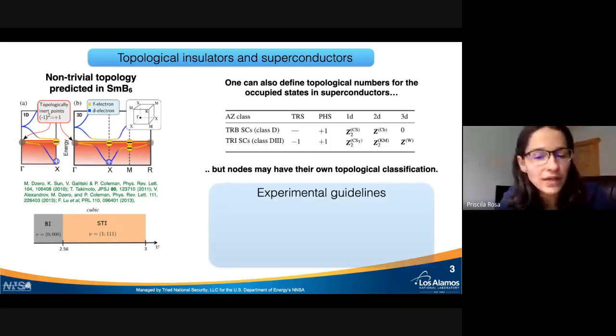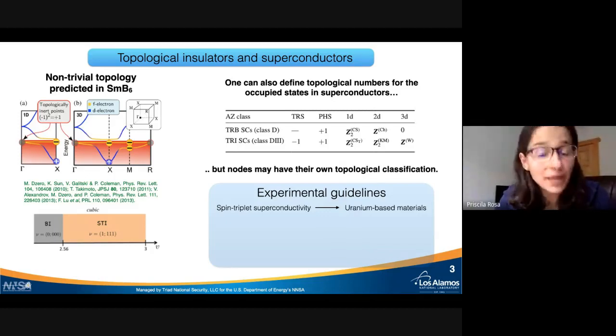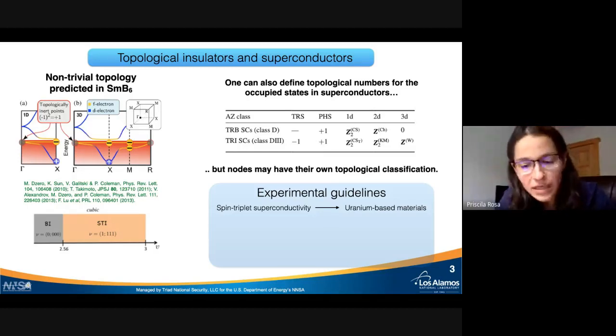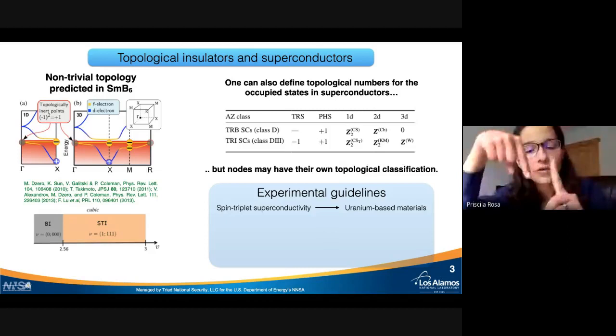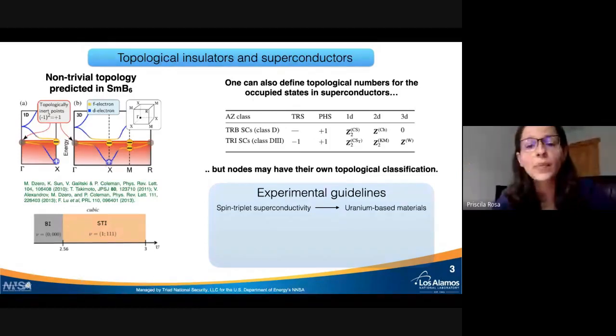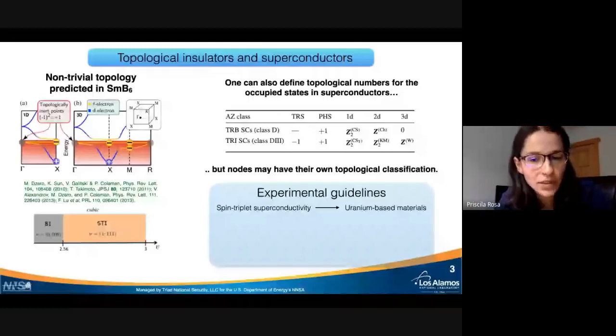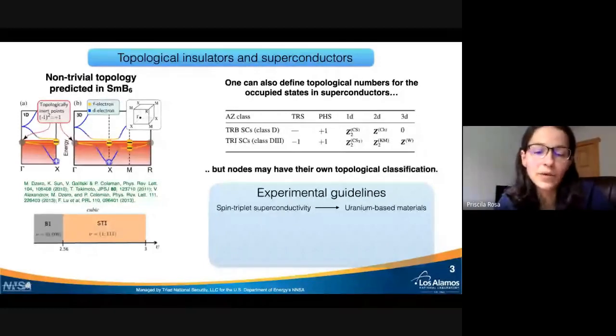And I want to start with an experimental guideline, because we know that topological superconductors tend to occur in spin triplet superconductors. Often in, let's say, BCS or phonon-mediated superconductors, we have a spin singlet pairing, so the spins are in opposite directions. But in certain uranium or f-electron-based materials, the spins are actually parallel. So you have the possibility of spin triplet superconductivity, in particular close to a ferromagnetic instability. This is going to be the experimental guideline for trying to find topological superconductivity.